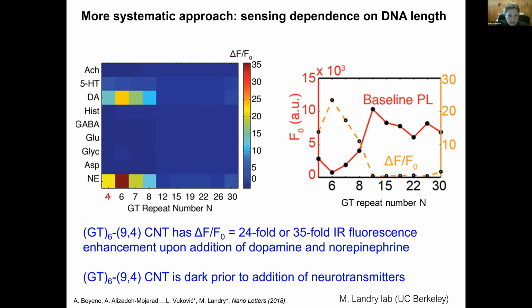And so in experiment, they checked it. We used the sequence called GT repeat. That just means GT, GT, GT, n times, and then sequences of different lengths. So some of them were GT4, GT6, GT7, all the way up to GT30. And here we have a heat map of whether this particular sequence is sensing the neurotransmitter. If it's red or yellow, it's a good sensor. If it's dark blue, it's not a very good sensor. So we could see that GT6, for example, is a good sensor for dopamine and norepinephrine in this case, and for nothing else pretty much. So GT6 turned out to be a good sensor. And all these longer DNAs are not very good sensors for these neurotransmitters. So that was the first initial measurement that was done.